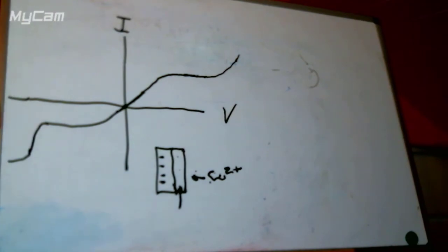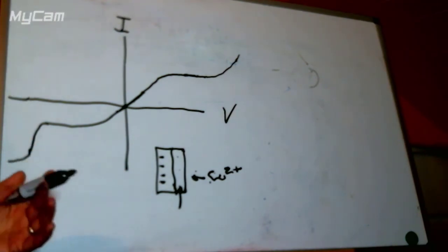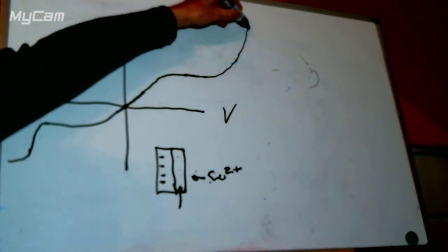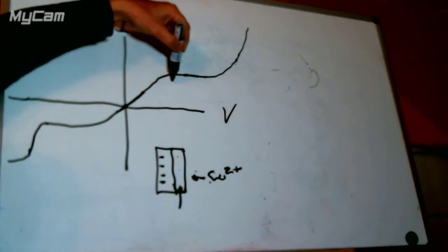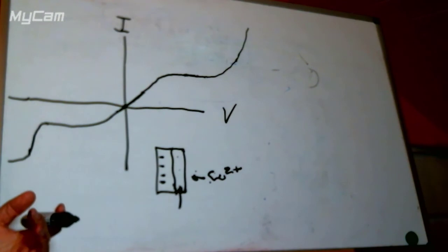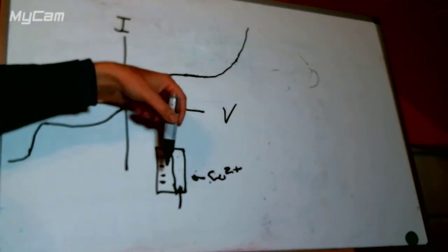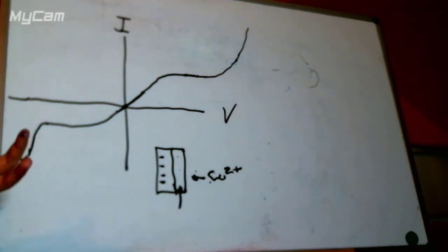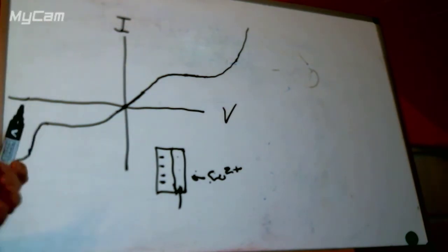If we are breaking the electrolyte in that case, there is comparatively more of it. So the potential amount of current that we can draw is way higher than the potential amount of current that we can draw from any other process, because there's a lot of electrolyte there. We're still limited by the electrode area, and in this case, if we're making bubbles at the surface, we will have weird things go on because we will be blocking parts of the area with the gas bubbles.